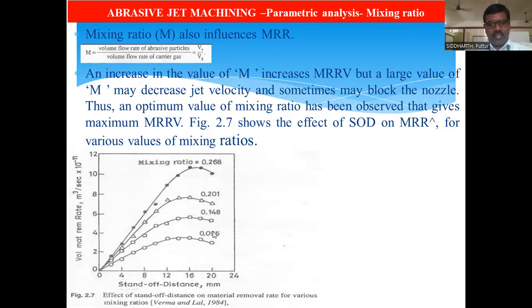Whenever the mixing ratio is increasing, the volume of metal removal rate is also increasing along with the standoff distance. So if the standoff distance increases, up to this 16 mm, you are going to get the maximum metal removal rate at 0.268 mixing ratio. All these are the mixing ratios. So at 16 mm, almost all of them give the peak metal removal rate. But if we still increase the standoff distance, then the metal removal rate comes downward.